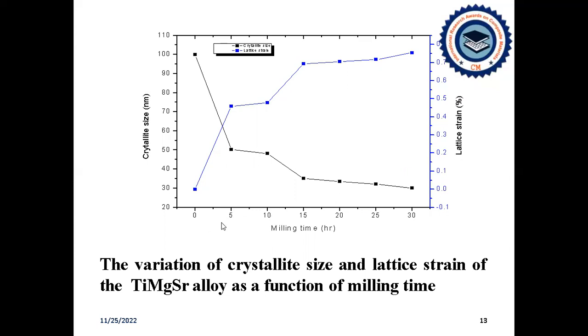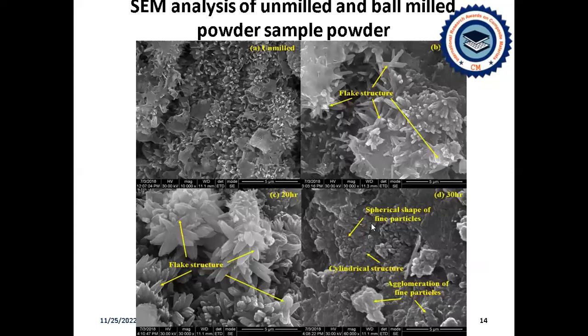As the milling progresses to 30 hours of ball milling duration, the crystallite size goes on reducing, and the blue color curve shows the lattice strain increases as the crystallite size reduces, due to the increase in the ball milling duration.